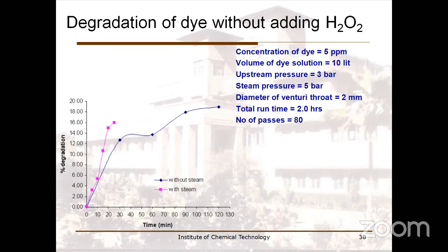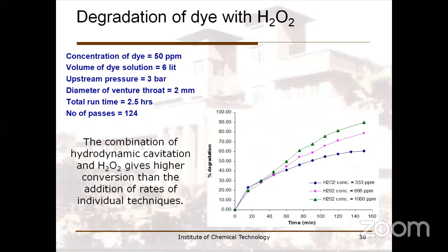So steam again is a gas when you are inserting it into the liquid, and with steam there was some difference because the blue line shows it without steam. So it's a slow degradation. With steam you are going to get a significant increase. If you look at 30 minutes treatment as a comparison, it's about 12 and about 16. So there is some increase with steam, but more importantly, we are going to look into the addition of hydrogen peroxide. About 10-20% degradation is happening without H2O2, only in the presence of hydrodynamic cavitation. With hydrogen peroxide, there is a significant increase and you are reaching almost 90%.